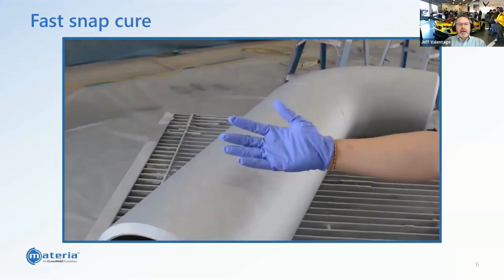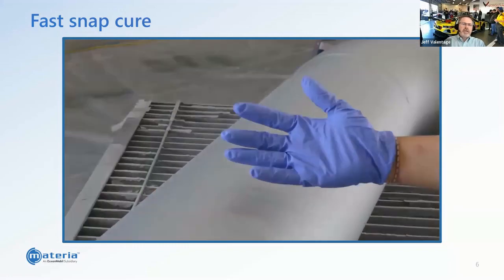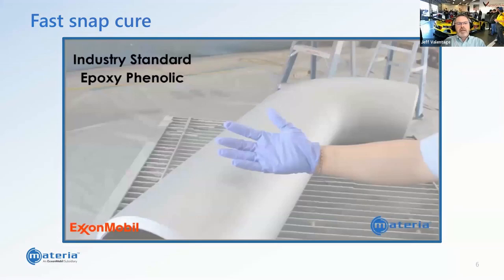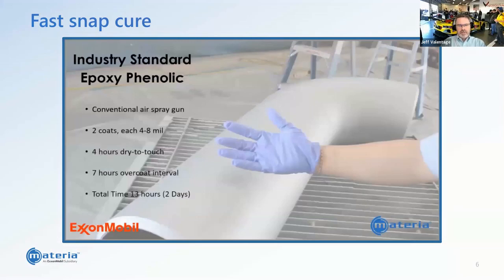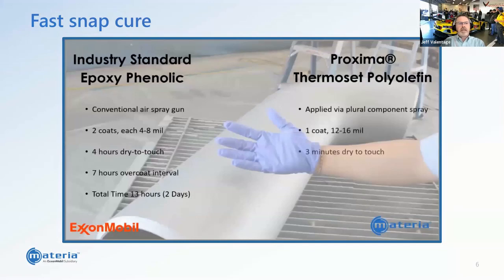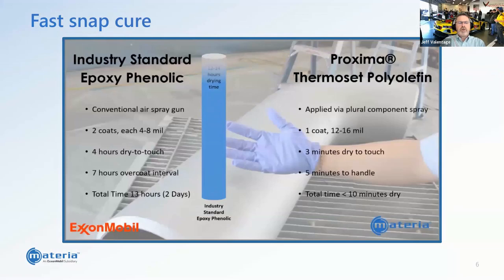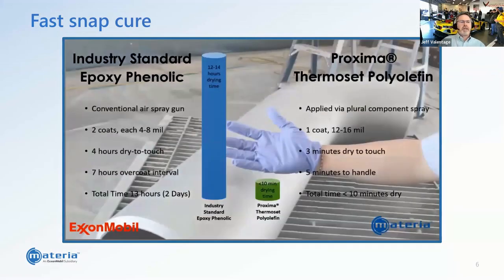So this particular application typically takes 2 coats. We can do it in 1 coat, and we can do it in significantly faster time. So this application, we were able to do this for this customer in less than 10 minutes. And it typically took the customer 12 to 14 hours drying time for this specific application. So again, just showing the versatility and use for this material.